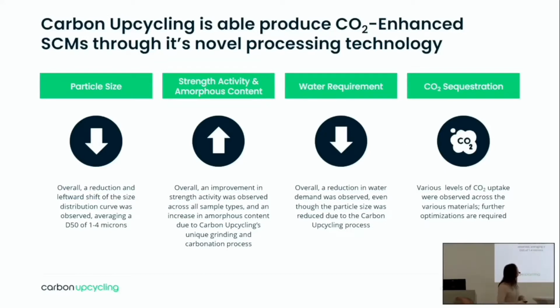There we go. Carbon upcycling was able to produce these CO2-enhanced cement replacements using our technology. And we looked at a couple of different parameters through different strength performance testing and chemical analysis to come up with our verdict if these materials were suitable for our process. So we see a reduction in particle size in the material. We increase the amorphous content, which helps to boost the strength activity of the material. We decrease the water requirement, making it a more sustainable material, so you don't have to use as much water. And we were able to determine different levels of CO2 absorption across the different materials.